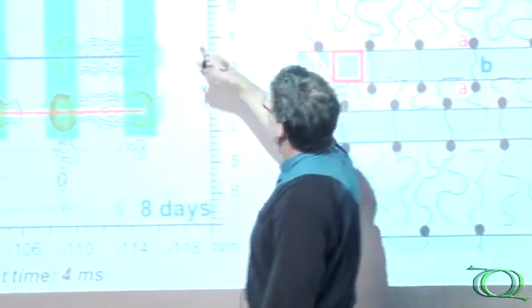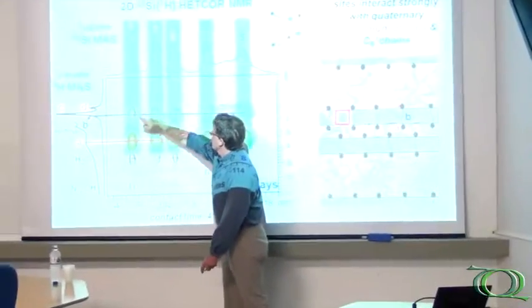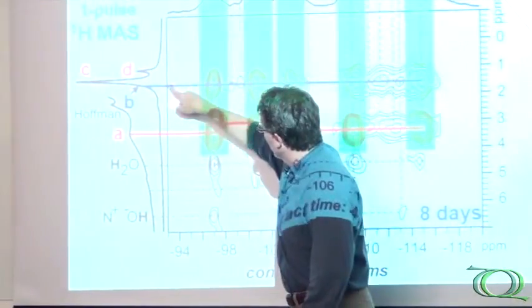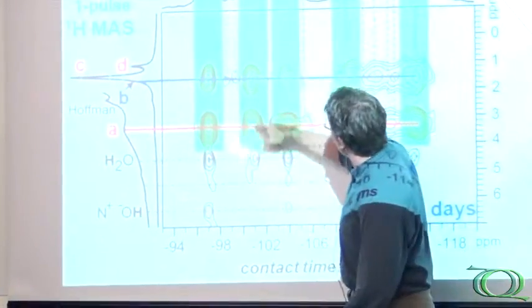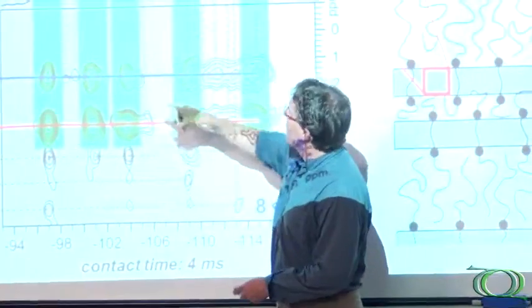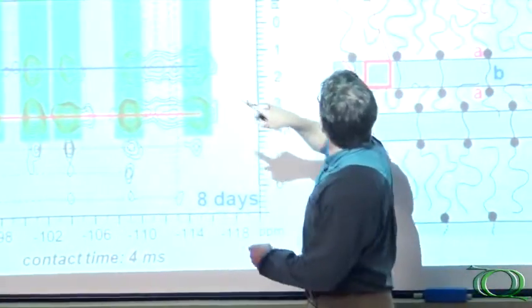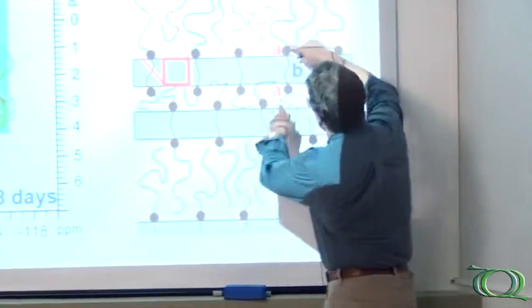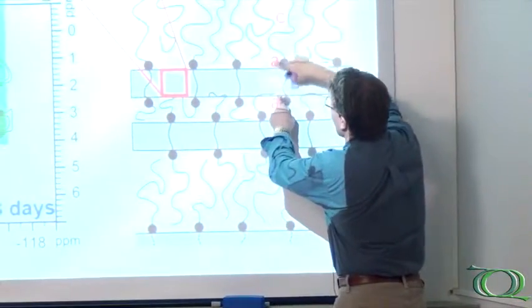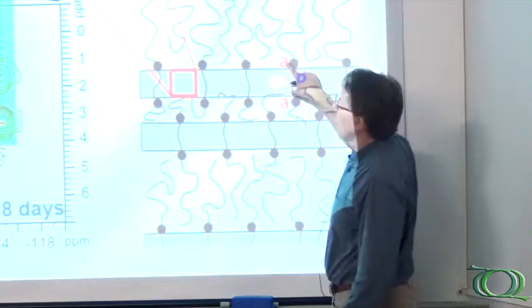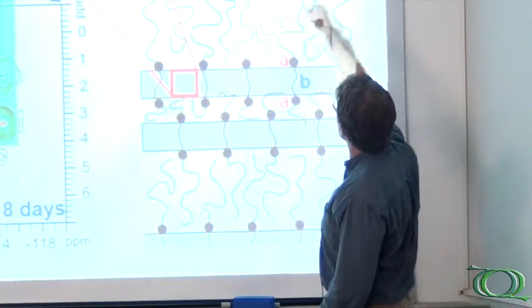And what you see is that in the green, you see that all five of these, as I mentioned earlier, are correlated with those signals which match up. So site one is correlated in B and with A, and same with all of them. They're all correlated with the same protons that are attached to the quaternary ammonium groups, consistent with them being and strongly interacting with the layered silicate sites of these silicate nanosheets. So all five layered silicate sites interact strongly with the quaternary ammonium groups and the C6 chains.